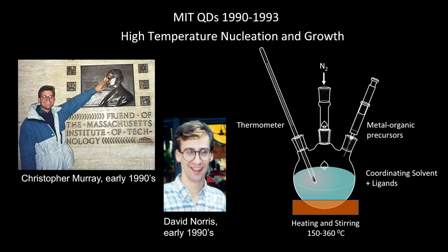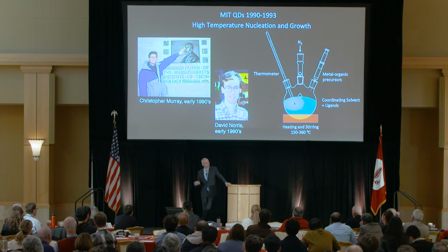And so we went to that, and that turned out to be really, really important, because now we had high temperature, and we were able then to create this, what is called now the hot injection method. So this is basically, we take our metal organic precursors that contain our cadmium and selenium, or whatever elements you want to put in there. We've got a solvent, a coordinating solvent where we use these octylphosphine compounds. High temperature, 300, basically as high as an organic chemistry can go. You know, organic solvents don't really go much higher than about 375, 400 degrees Celsius before they start falling apart. So we basically push the limit of organic chemistry, organic solvents.